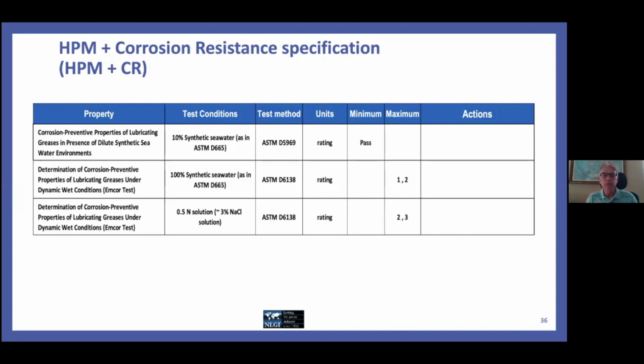The D5969 is the saltwater version of the standard D1743 rust test, and we're doing it with 10% synthetic seawater as specified in ASTM D665. And again, this is a test that just has a pass or a fail rating. Then we've added 2 dynamic tests. These are both based on the Emcor test method, D6138. They're dynamic. The first one is using 100% synthetic seawater, as in ASTM D665.